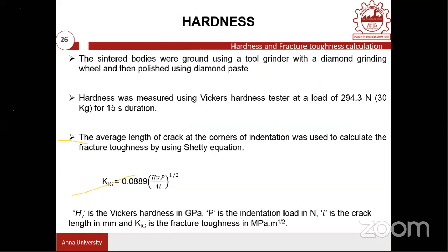After fabricating the CERMETS by spark plasma sintering, we can measure the hardness value by a Vickers hardness tester, and the toughness can be measured by the Shetty formula. Toughness is a really challenging measurement in ceramics. In conventional metals and alloys, we can take the stress strain curve, and the area under it is equivalent to the fracture toughness of the material, because it is the energy absorbed before fracture, or the energy to create a fracture. That is, how much energy is required to create a fracture. That is the value we take from the stress strain curve.